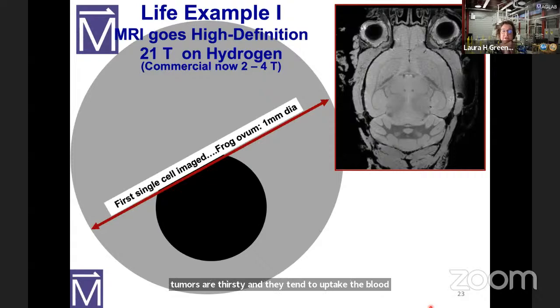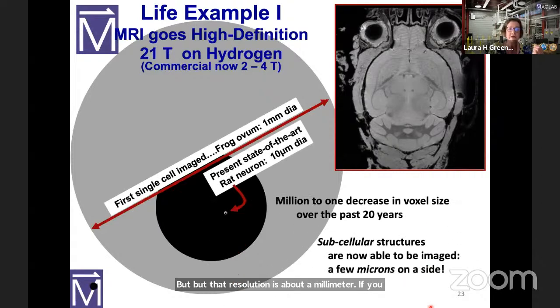But that resolution is about a millimeter. If you go to 21 Tesla, you can go to 10 micron resolution. So that's the increase in resolution. So now you can see subcellular structures. Now, as many of you know, when you're in an MRI machine, they're switching and putting on different kinds of fields, and you follow that with an RF frequency, and you're doing the spectroscopy using RF frequency. So one of the reasons why this resolution is so much higher at 21 Tesla is because you're using higher and higher frequency for the magnetic to RF frequency resonance condition. So if you're using 10 or 20 times higher frequency, then you have 10 or 20 times higher resolution.